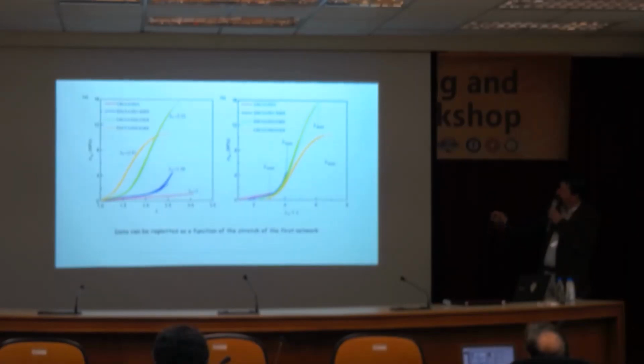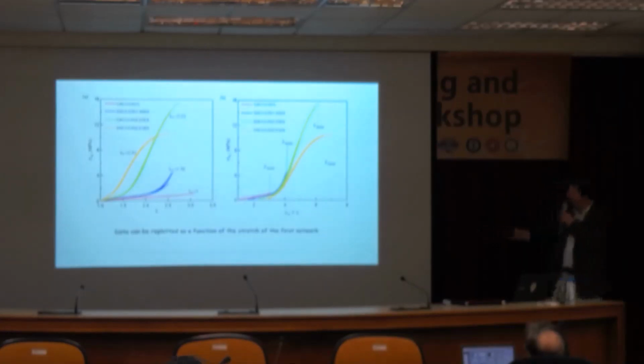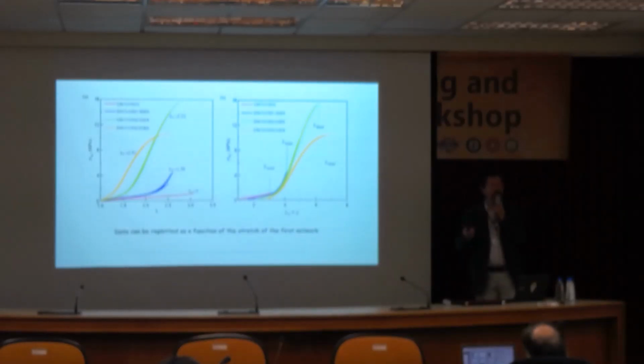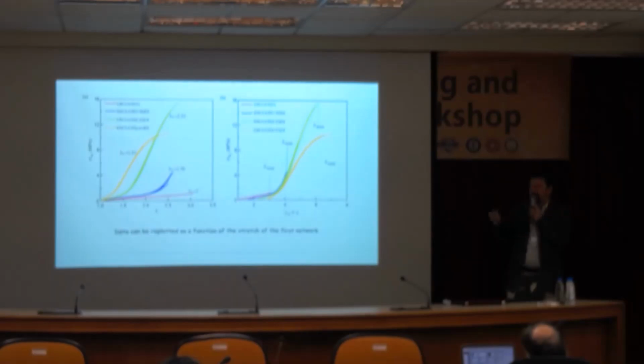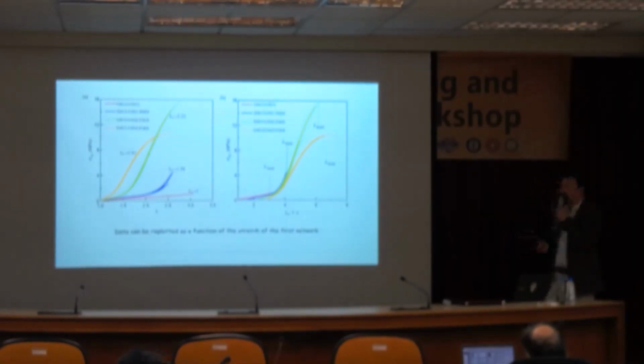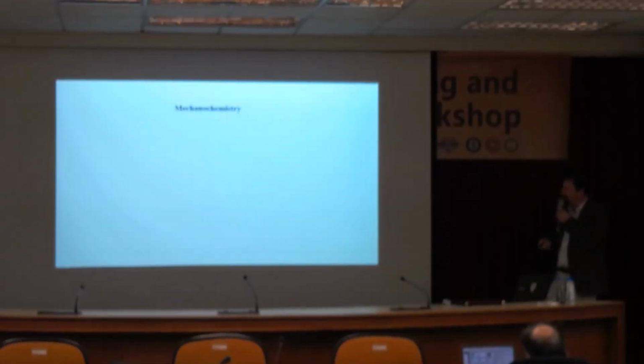Now these 4 curves fall into something that looks like a master curve. Here it is different, the stress is different. But what I would like to point out is that now this is really the stretch of the initial network that we're plotting here. And it actually breaks much sooner for the sample that we made initially. As we embed the sample into a matrix, the stretching increases more and more. So this is exactly the opposite of what we would have predicted from the molecular standpoint. If you pre-stretch, you will break sooner. But here you can see that the network is actually breaking later and later. It's being protected by that matrix network. This is an intriguing result that is much more general than this model system.